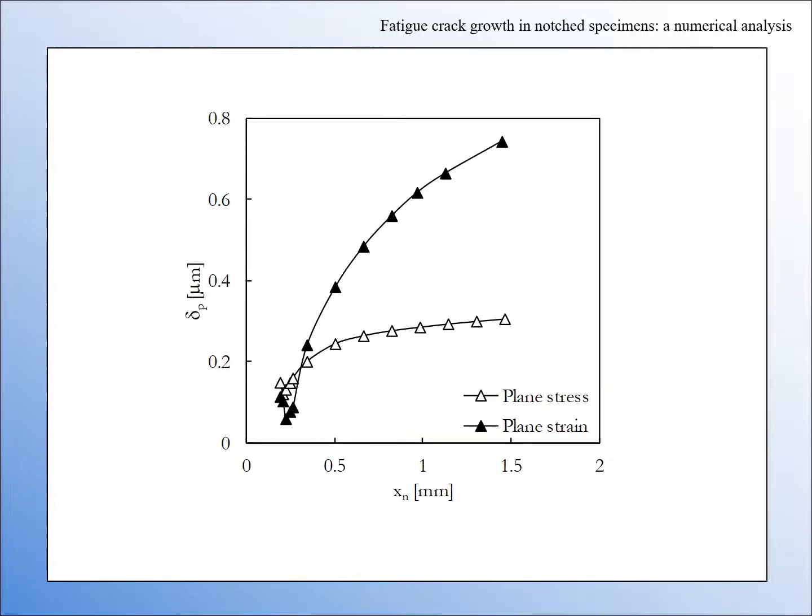Here you can see the influence of stress state. Results for plane strain state are above results for plane stress state. This indicates that fatigue crack growth is faster under plane strain conditions.